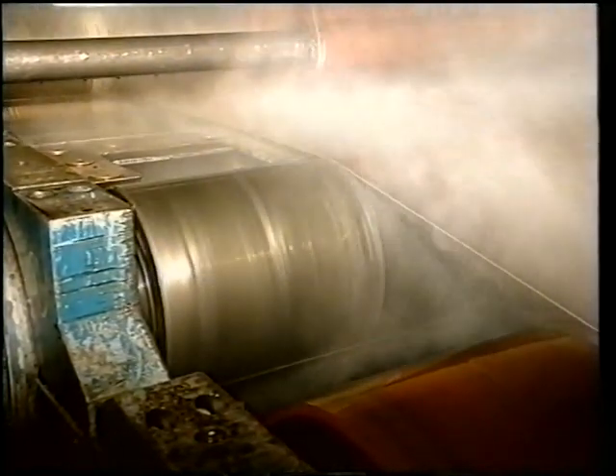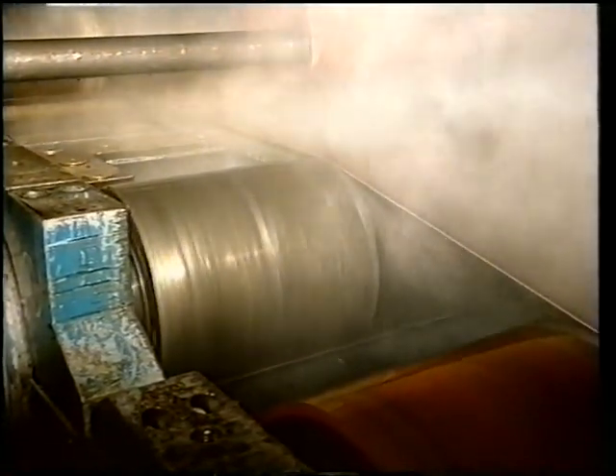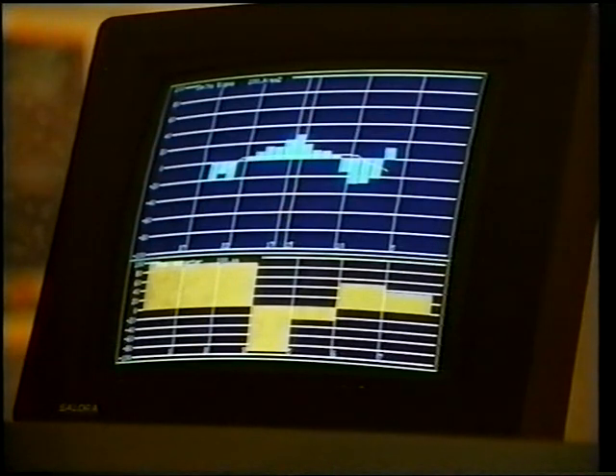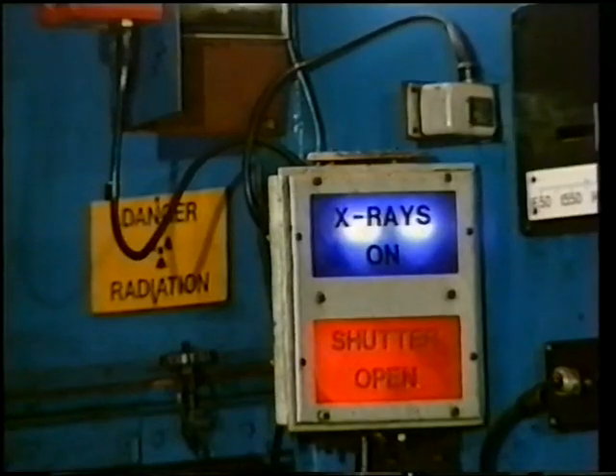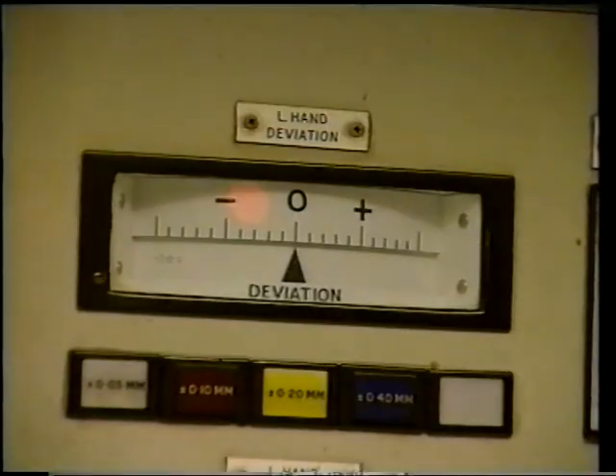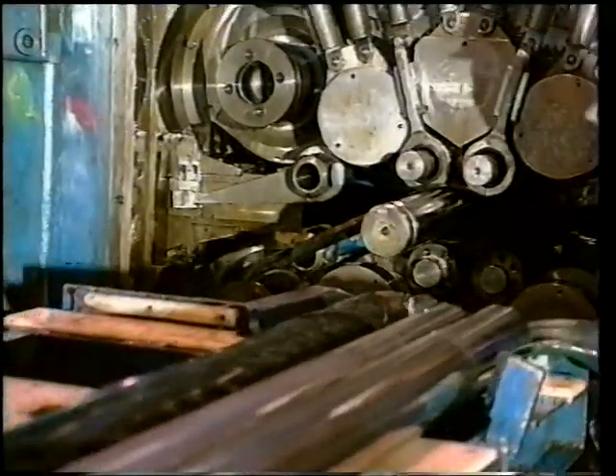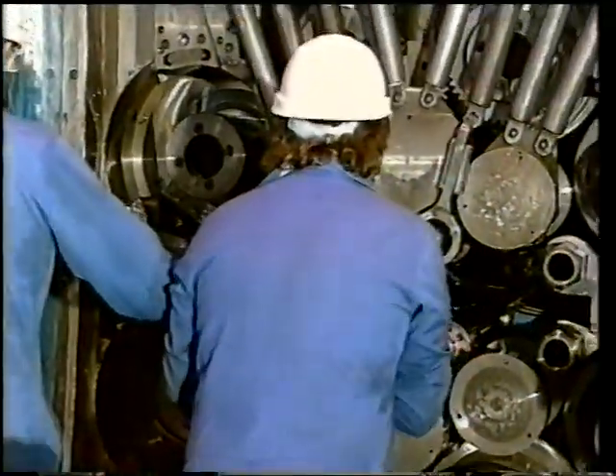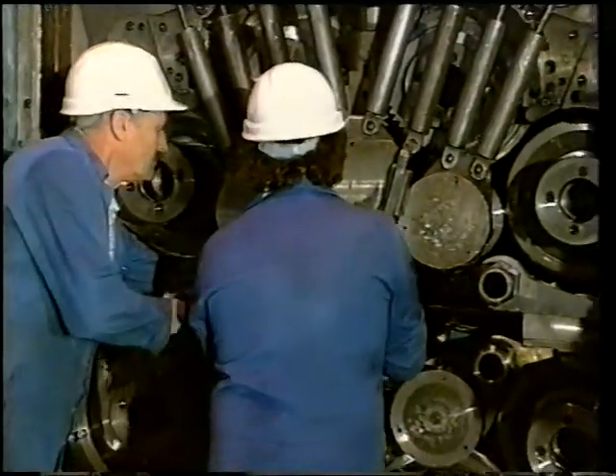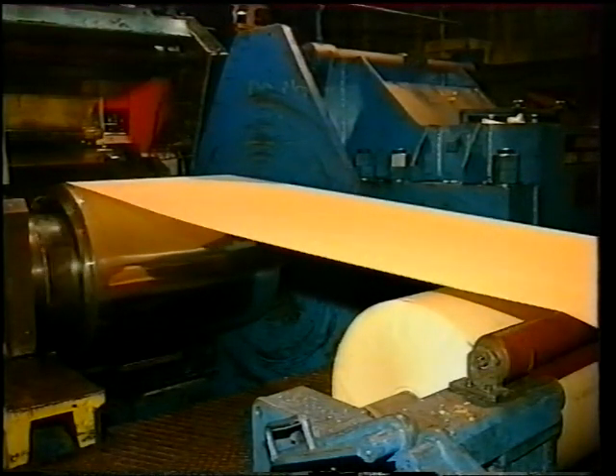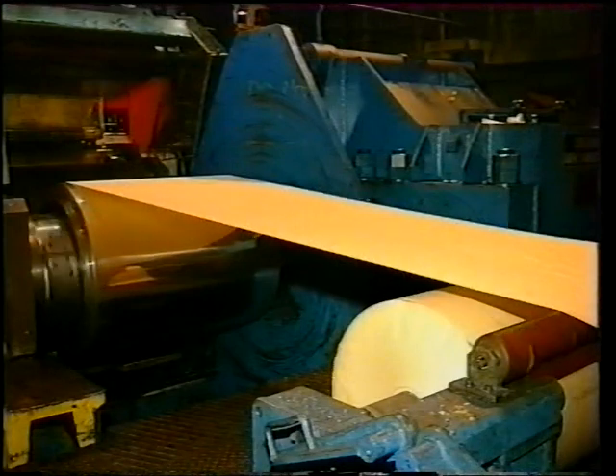Stressometers, pressure-sensitive rolls, fitted to the ingoing and outgoing sides of the mill give an indication of the strip shape, and X-ray gauges measure strip thickness. Freshly ground rolls are used for the final pass of each coil, and the stripped surfaces are interleaved with paper to further protect the finish.